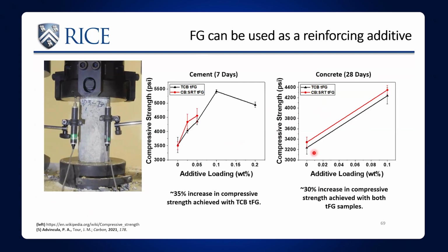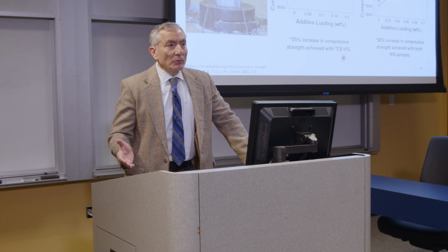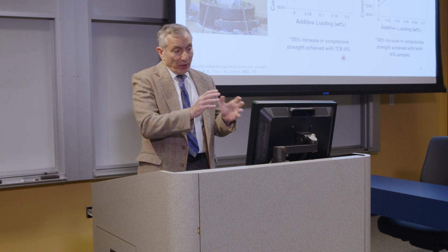Here's how you test concrete. You make these blocks, and then you go over to Ryon building, and they have these crushing concrete. And so that's our building where we go to do civil engineering studies. And so you want to see how strong is that concrete. And so you have these systems that can crush concrete, and you're measuring how strong is this concrete in the sense of a compressive strength. And you can see when you're adding in material here, so 0% addition to 0.1 weight percent addition, you can see that there's an increase in the compressive strength on an additive loading. So you get about a 35% increase in the compressive strength by adding tire carbon black turbostratic flash graphene, meaning you can take waste rubber tires, the carbon black that comes out of waste rubber tires, and you can turn it into graphene, which is turbostratic, remember has no ordering of the layers, and then you apply that to the concrete.